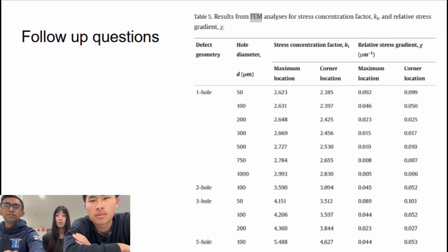So a little commentary. An interesting insight from this paper was a specific detail about where the cracks formed. Cracks typically initiate where stress is concentrated, which in theory should be the equator of the hole. But looking at the FEM data and the samples, the cracks started at the corner of the hole. This highlights a gap between textbook theory and reality, and suggests that surface finish and drilling techniques matter just as much as the hole size.